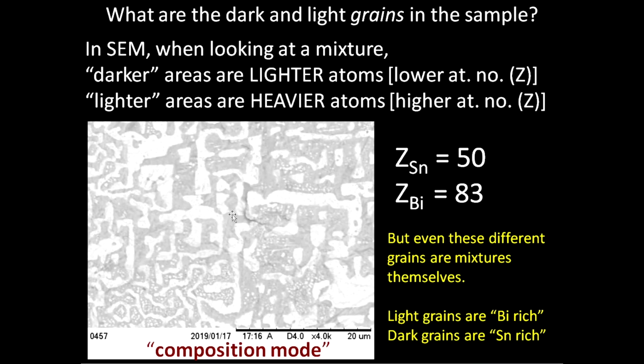When we did the lab, we just assumed that these two things mix together when they form an alloy and make a homogeneous mixture. But at the microstructural level, it actually turns out things are a lot more complicated. They don't seem to want to mix together. Tin likes to hang out with tin, and bismuth likes to hang out with bismuth. And so you get these regions of separation.